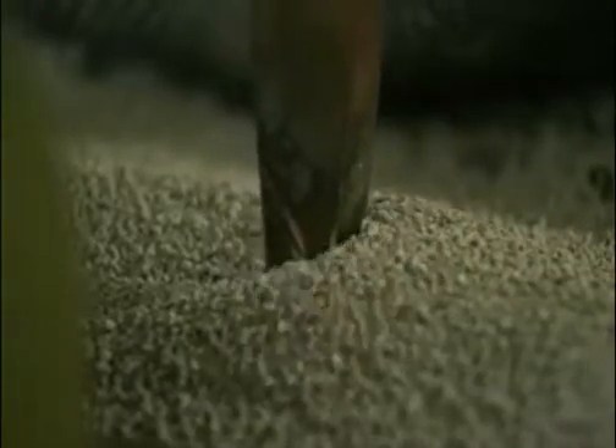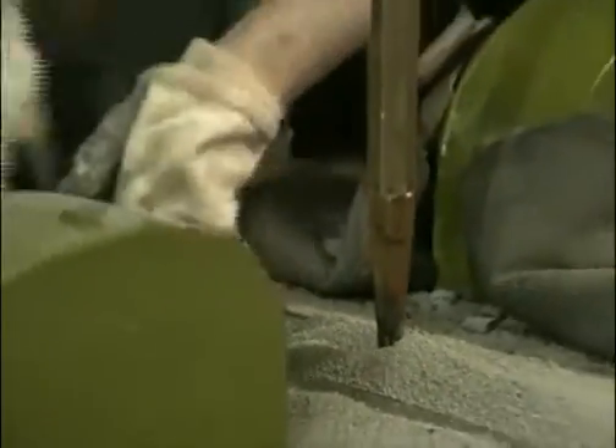Slow motion photography shows that at low welding currents, metal transfer occurs by the end of the wire dipping in and out of the weld pool. This is called dip transfer. At higher currents, molten metal sprays across from the end of the wire into the weld pool. This is spray transfer. Submerged arc welding also uses filler wire, but the weld is shielded by a blanket of flux instead of gas.